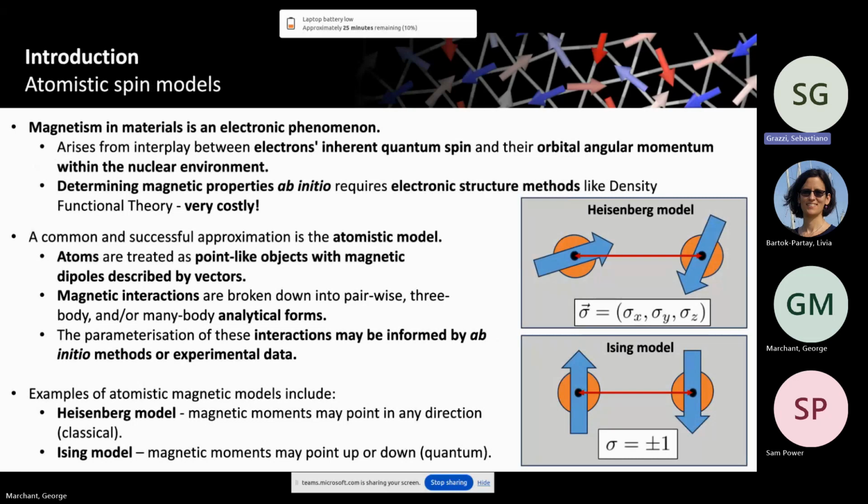just as a bit of insight, in order to accurately study magnetism, you really do need to get to the electron level. So you need to be performing ab initio calculations from first principles, which include the electrons. You can do that, and there are more and more ways of doing that on large scales, but it is still a very expensive method, and particularly when you include magnetism, it becomes even harder to converge these electronic structure methods.